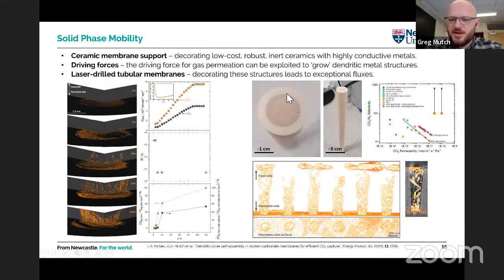And we can do the same thing. I talked about the laser drilled structures with the beautiful parallel pores. So we can grow these same silver structures within these pores and get very, very high performance membranes. So the plot that I showed you on one of the early slides actually comes from this membrane. These points here, very, very high permeabilities, very high selectivities, comes from this membrane decorated with silver. So very, very high performance using low cost ceramic, but with a very small amount of a high cost metal.